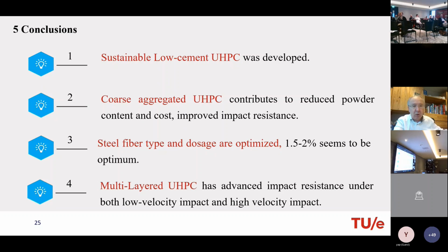Well, we managed to make a low cement UHPFRC by substituting cement by limestone powder, for instance, and also reducing the silica content. The total powders as such we could reduce by coarse aggregated UHPFRC, by adding these coarse aggregates that reduce the powder content and then also the cement content. Also, the steel fiber is optimized. Well, here 1.5 to 2% seems to be optimum. Well, I dare to say that 1% could be good already with steel fiber.